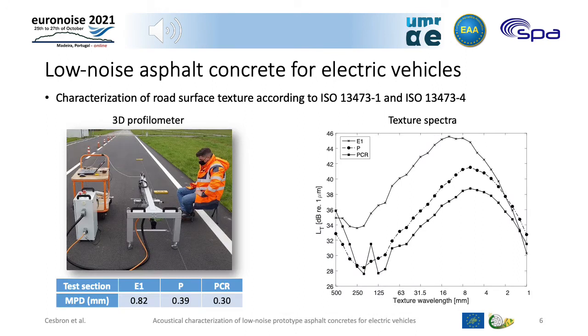Different properties influencing tire road noise have been measured on the 2 test sections. The road surface texture has been measured according to ISO 13473. It was measured by means of a 3D profilometer. Then the mean profile depth was calculated from the extracted profiles. As you can see, the MPD on both prototype test sections was much lower than on the reference test section E1. It was 0.39 mm for test section P, 0.3 mm for test section PCR, and in comparison 0.82 mm for test section E1.